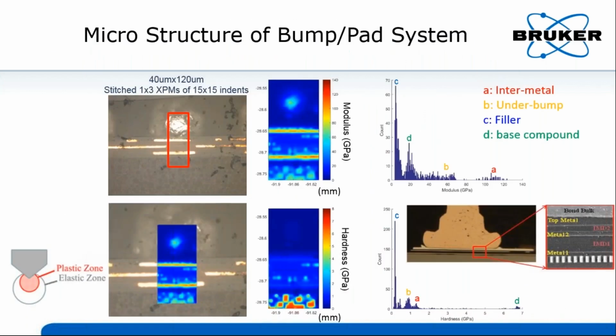Here we go to the first example of an indent array for observation of the distribution of mechanical properties. The sample is a bump and pad system, mounted well and polished well. The bump was totally mounted, and the surface for testing is mainly the pad structure, including the two intermetal layers, the filler between the two intermetals, and the compound of the sublayer.